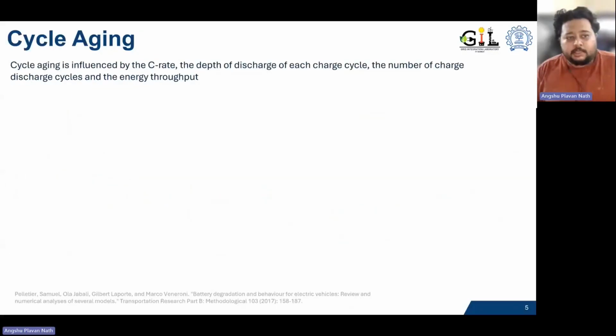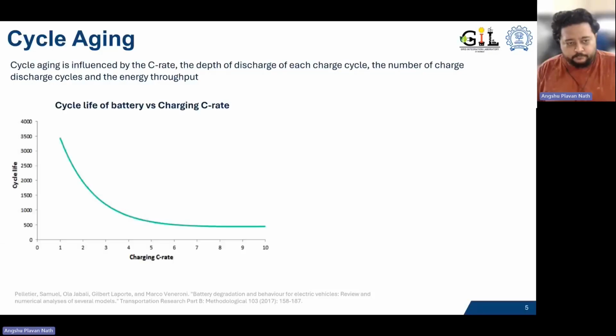Coming to cycle aging, it is influenced by your current, the C rate of the charge and discharge cycle, the depth of discharge for each charge cycle, and the number of charging and discharging cycles we go through. If you look at the charging C rate, 1C means that for a battery with X kilowatt-hours, it takes exactly 1 hour for the battery to be full. That's how C rate is defined. As we increase the C rate, with faster charging of a battery, our cycle life decreases almost exponentially.